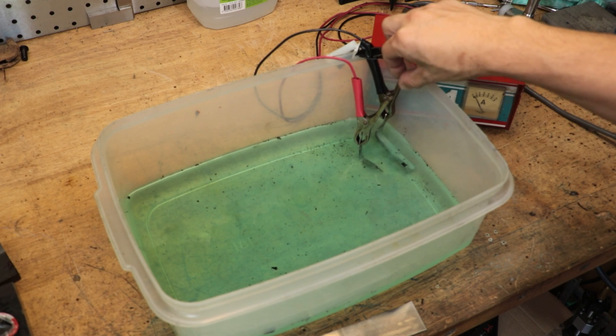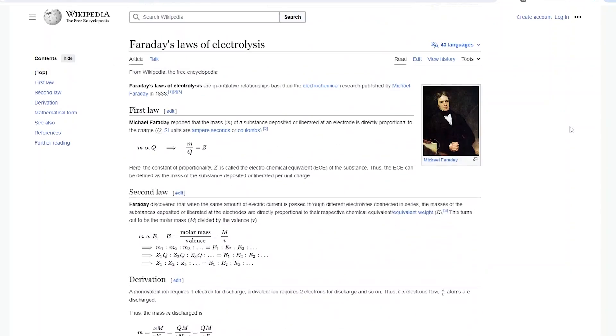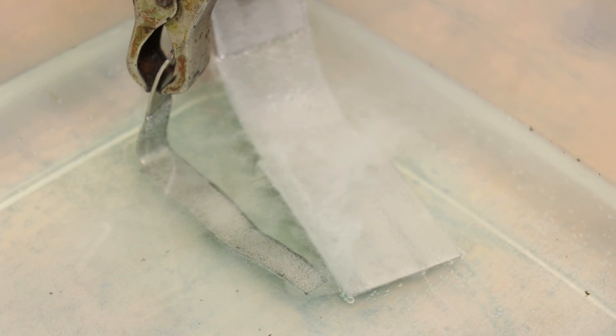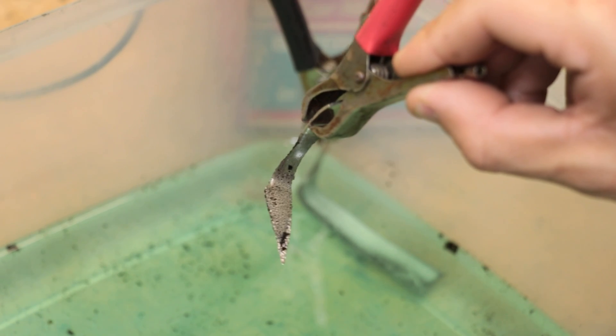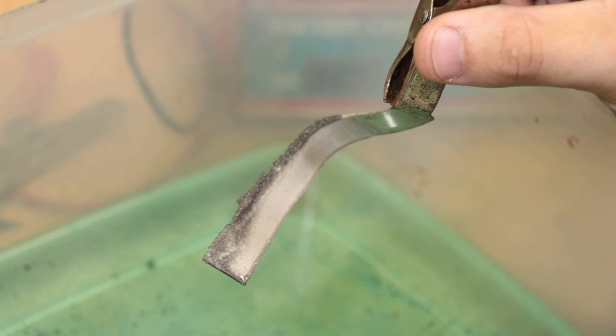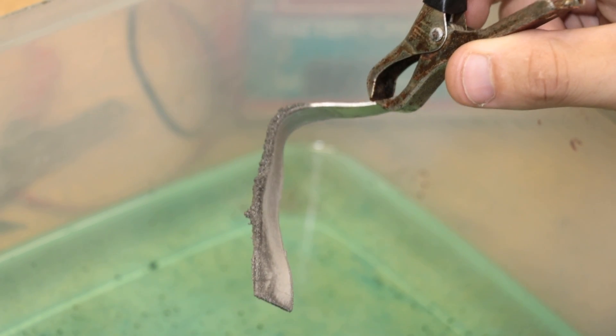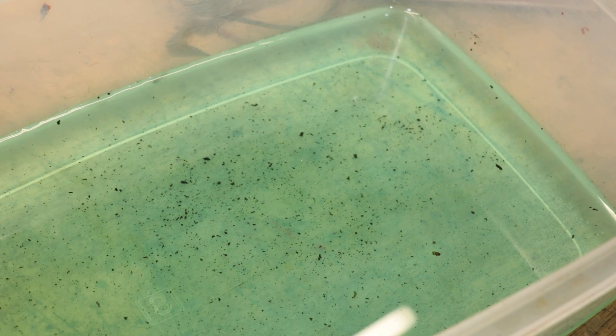At the end of the day, what we're really focusing on here is the amperage, not the voltage. And if you really want to know why, it's all tied up in Faraday's laws of electrolysis, which we can actually use to roughly estimate how long it might take to dissolve the nickel. It takes 1 amp of current for 1 hour to dissolve roughly 1.1 grams of nickel into the solution. I had it at about 3 amps most of the time for the 2 hours that I ran it, so I should have dissolved about 6.6 grams in total. Obviously it won't be this much because it's not 100% efficient, but it should give us a rough estimate. And you can definitely see just how much has dissolved into the solution. It should be also pointed out here that the cathode has picked up some nickel too from the process, but not as much as has been put into the solution. There's also a bunch of black particulate matter left at the bottom. I believe this is insoluble impurities from the nickel plate, and I will need to filter that out.